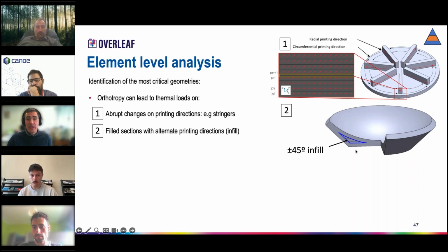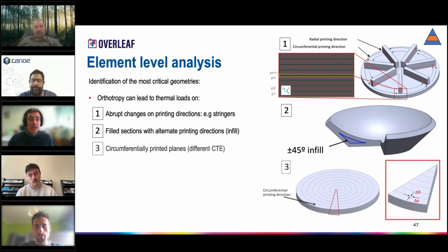A second point is that if we have zones too thick, or thick zones, maybe we can have infills printed at plus minus 45 degrees. So this means different orientations and different thermal stresses. And the third point is that even if we print circumferentially, we will have different thermal expansion coefficients. So there are certain zones, for example this central part, that can have higher stresses.